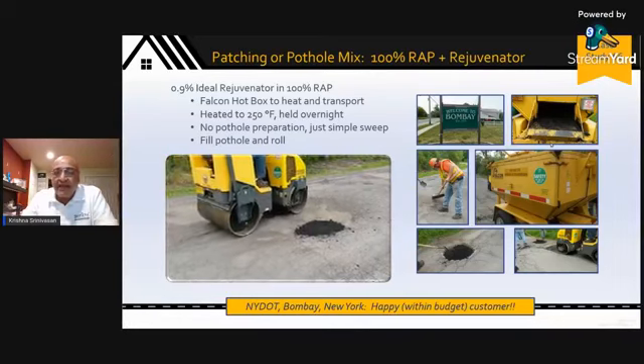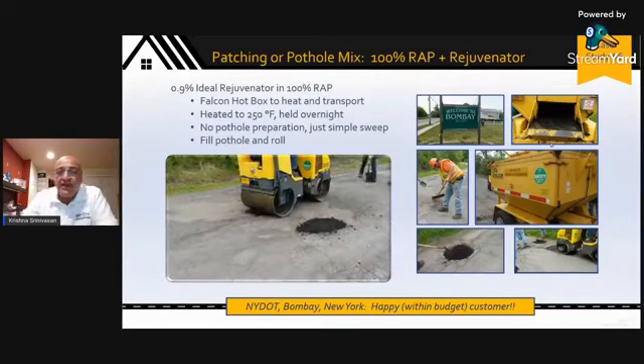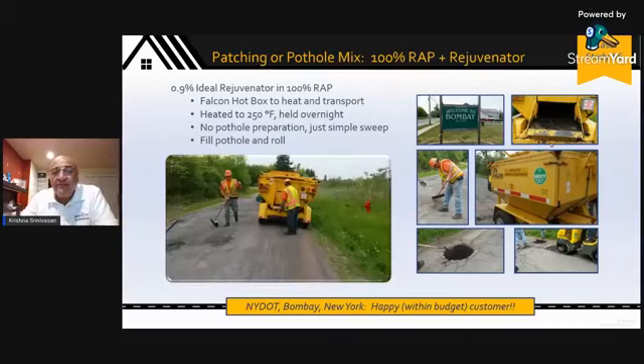You roll it to the job site. You put the mix into the pothole, and then you roll it over, and it's opened up to traffic immediately. So it's also used not just in case of hot mixes made in plants, but also for pothole filling and shoulder repair and things like that. Rejuvenation with 100% RAP is a very viable technology to provide relief when you have emergency roadway repairs.